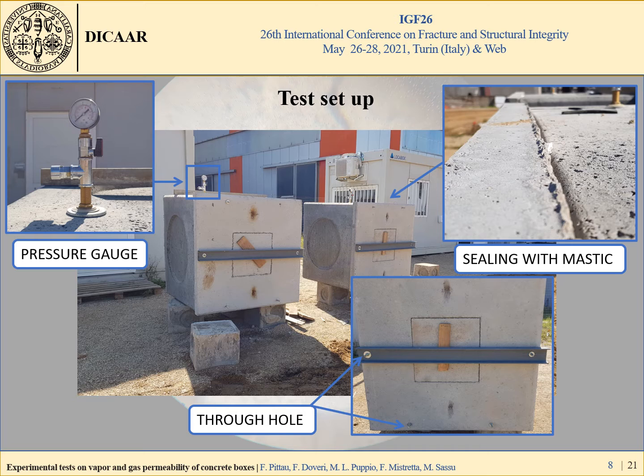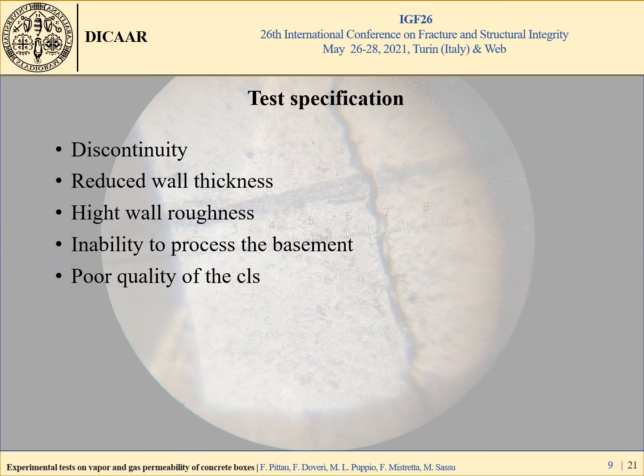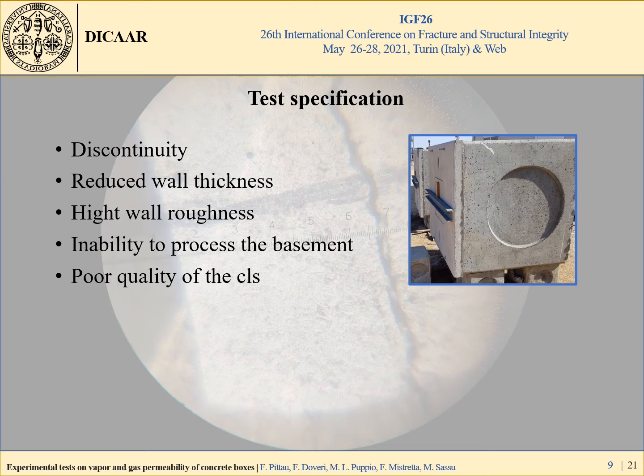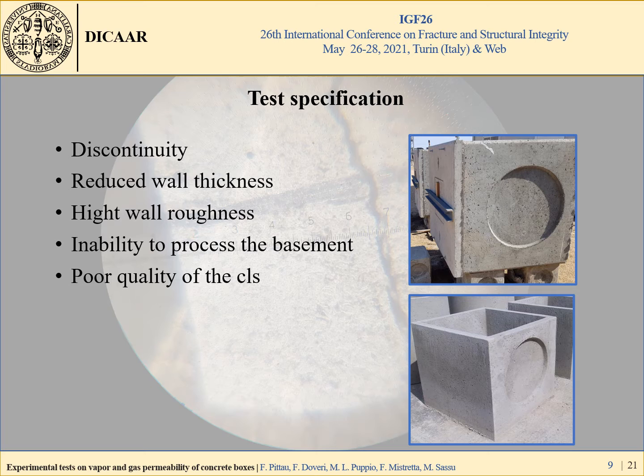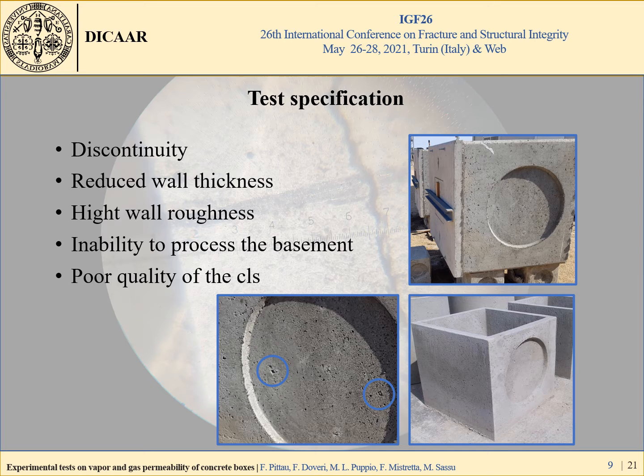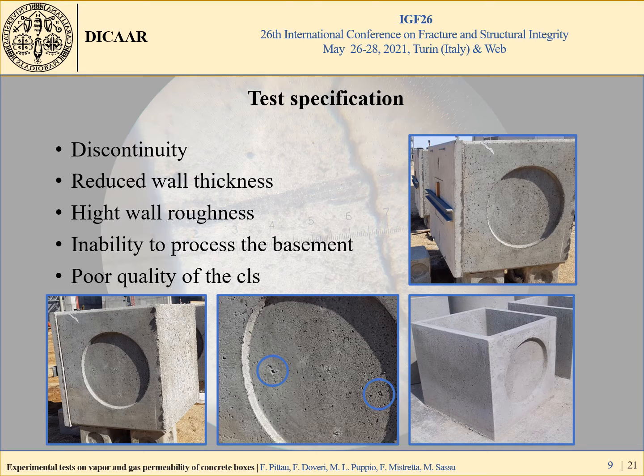The test consists of applying an internal pressure with nitrogen gas and verifying pressure and leakage. Here it is possible to see the characteristics that make the external coating test very difficult. First, the discontinuity of the material between the pit and the core. The wall thickness of about 5-10 centimeters. The roughness of the wall and the presence of specific deflection that are very difficult to work with. The impossibility to work on the substrate due to ruggedness and the inaccessibility of the surface, and the poor quality of the concrete, very difficult to find in a real concrete tank.